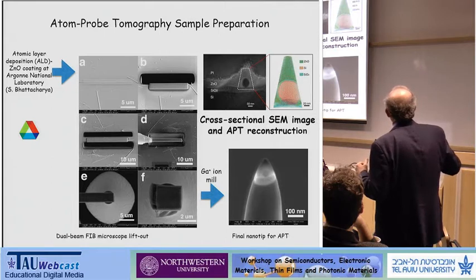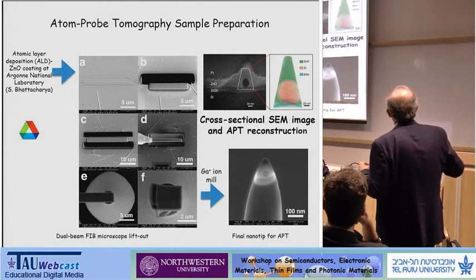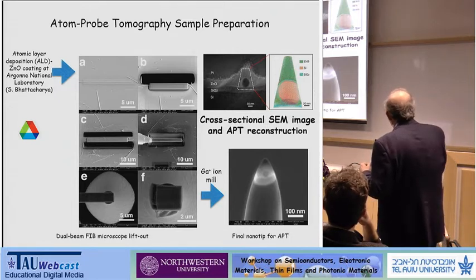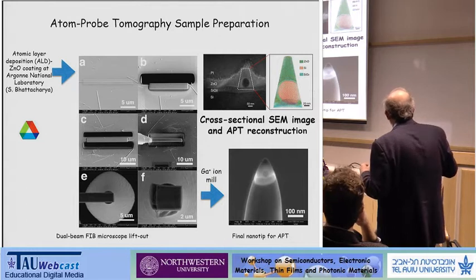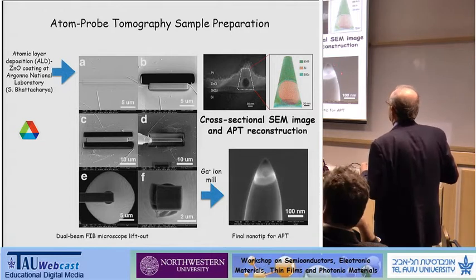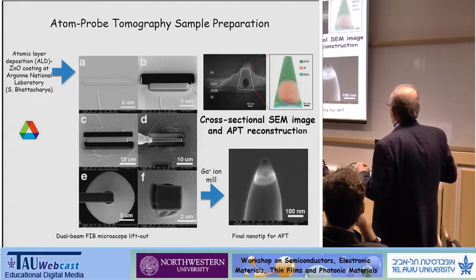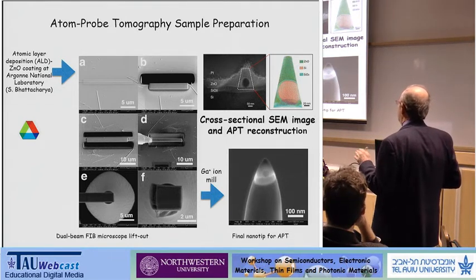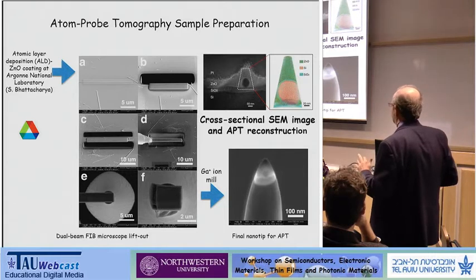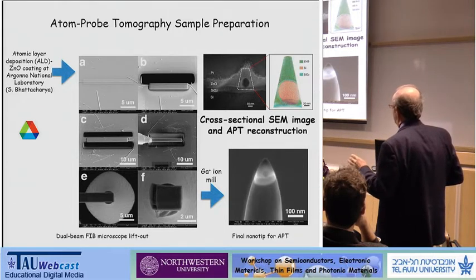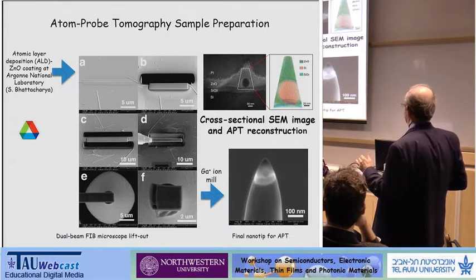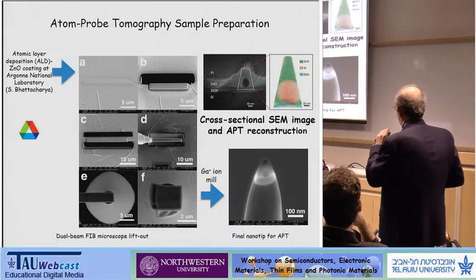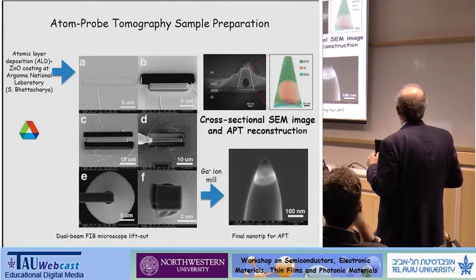And now if you look over here, this is the atom probe image. And you can see the cross-section of this same silicon nanowire in the specimen. And this is the end product here. So you have a nanotip with this silicon nanowire sitting this way, a section of the silicon nanowire. And I'm not going to go through these steps again, but I just want to emphasize it would be impossible to do this without a dual beam FIB. So for this field, as well as for other fields, the dual beam FIB is a real game changer. Before this, we were really restricted to just making specimens, nanotips, using electropolishing.